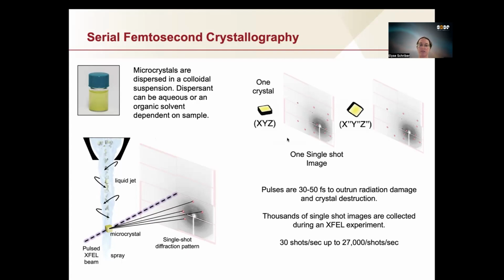And the way that SFX works is it combines both single crystal diffraction and powder diffraction. Rather than having one single crystal rotated through the beam, you have randomly oriented microcrystals that are delivered to the interaction point, and that pulse takes one partial diffraction pattern. So you get one single shot partial diffraction pattern of that one randomly oriented crystal. Then you collect thousands and thousands of these shots of randomly oriented crystals, so you can sample every possible orientation, but you don't know the orientation. It's random and basically produced by this dynamic dispersant that we use, the liquid jet.